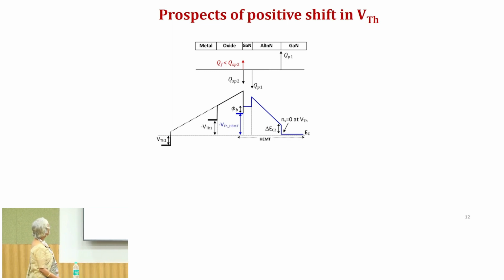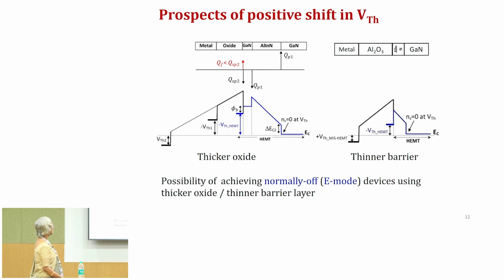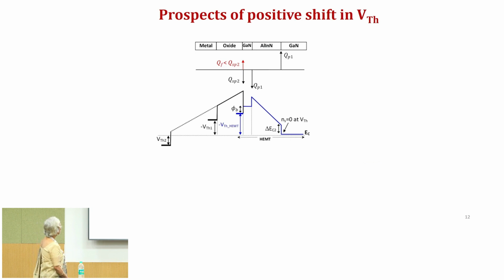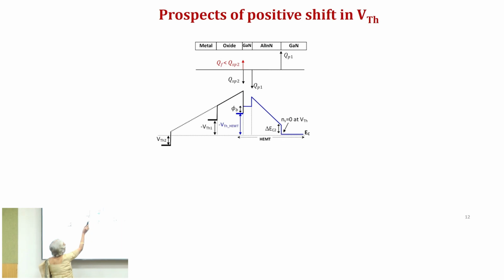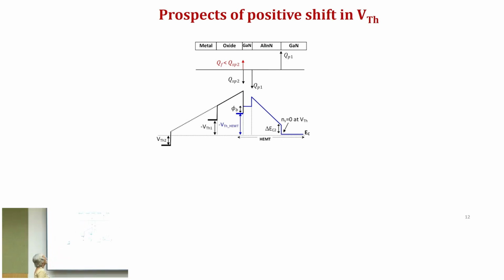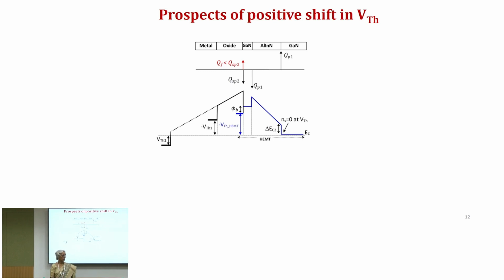So, this is an energy band diagram of the system we have. We have an aluminum indium nitride gallium nitride heterostructure with a thin gallium nitride cap, an oxide and a metal. And if you look at this, then you find that one possibility is that we can go for a thicker oxide. Okay. So, you see, this is the threshold voltage of the HEMT. If we have more negative charges at the oxide gallium nitride interface, then of course, the threshold voltage is going to increase, and we are going to have a more positive threshold voltage for the MISHEMT.